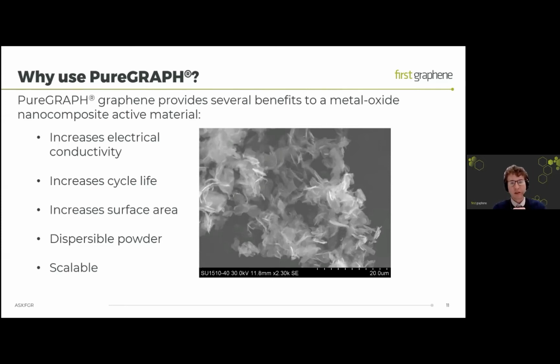We're also increasing the surface area, or the accessible surface area. So these metal oxide nanoparticles are quite high surface area materials, but then you're also combining that with graphene. And one of the benefits of this is the whole system would be supplied as a powder. So you would get these graphene platelets coated with metal oxides. It would be supplied as a powder. It would be able to fit into currently available processes, and you'd have these new materials ready to be used as electrode materials.